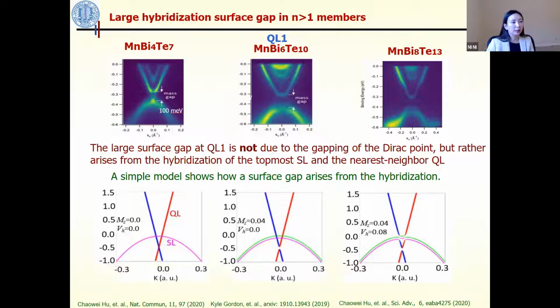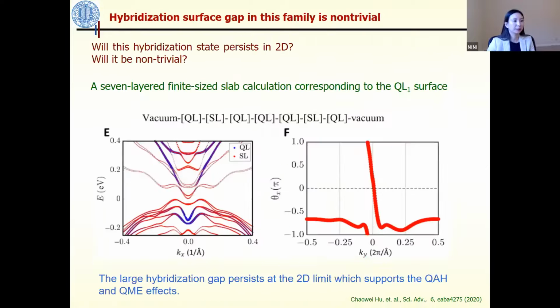However, when you turn on the VH, which is the hybridization strength, you can see besides the Dirac cone gap, you start to have an extra gap. This extra gap is the so-called hybridization gap, and this is what we observed in our experiment here, this large gap. So the next question is: at the beginning we said if we want to realize QAH, we want to open a gap at the surface Dirac cone. Now we have a large surface gap, but it's not a gap on the surface Dirac cone, but rather a large hybridization gap.